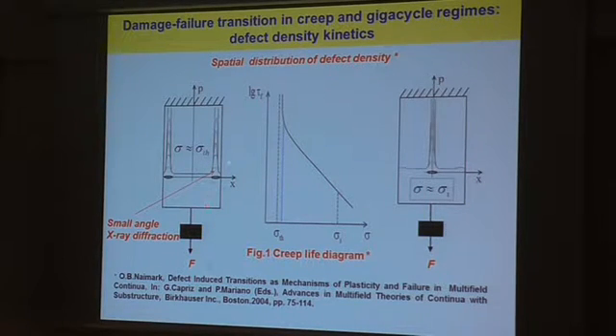To come back to the possible nature of crack initiation in the bulk of the sample, I would like to attract your attention to our experimental and theoretical results that were obtained around 30 years ago, when we investigated in situ different stages of damage evolution under creep conditions, combining the sample in situ with small angle X-ray scattering, which allowed us at different times to estimate the spatial distribution of defects.